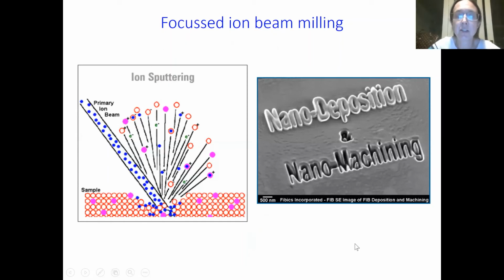We're going to make our needle-shaped specimen with something we call focused ion beam milling. Basically, in an SEM, we use a focused beam of electrons to image. In a focused ion beam microscope, we can image with the ions, but we can also use them in a very exact fashion to sputter away, dig holes in the sample. Like this, where it says nanomachining, that's a hole dug with the ion beam. Or here where it says nano deposition, that is where we have used the ion beam to induce deposition of a metal, which we've done by introducing a metal containing gas and then breaking it down with the ion beam. So we can do all sorts of things with our focused ion beam.